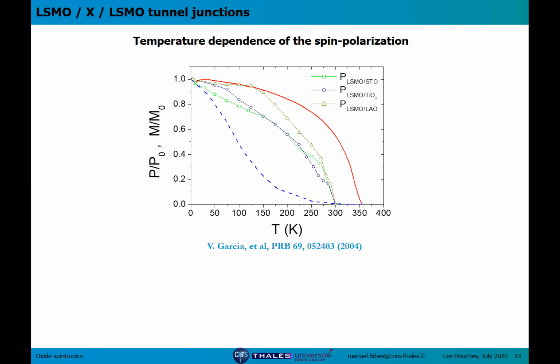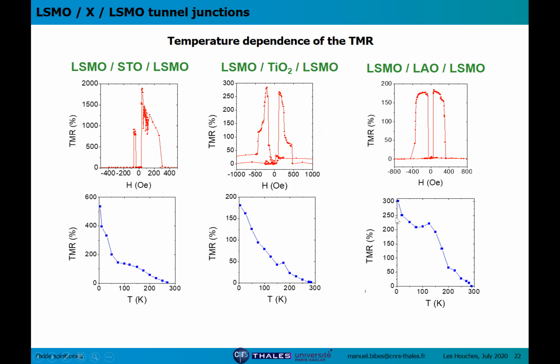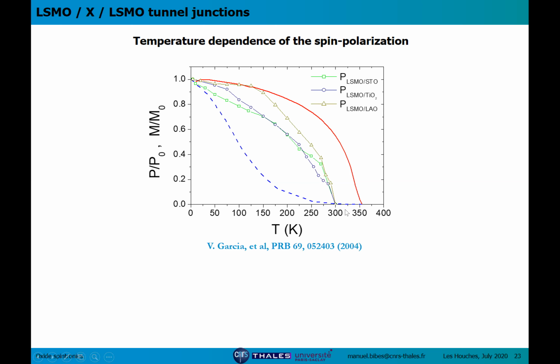But what we wanted to show with these experiments is to gain a little more insight into the temperature dependence of the spin polarization of the LSMO at these different interfaces. The three curves here with the green, blue, and brown symbols are the spin polarization extracted from this data. And the blue curve is the spin polarization measured by spin-dependent photoemission of a surface of LSMO. This was measured quite early on in the study of these tunnel junctions. Basically, the message here is that the spin polarization of the surface decays much faster than the spin polarization of the interfaces.